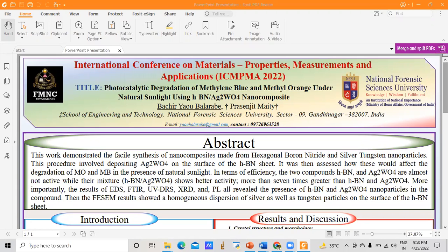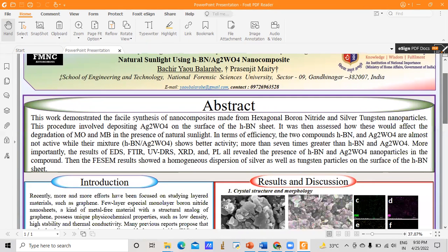So our topic is the photocatalytic degradation of methylene blue and methyl orange under natural sunlight using HBN-Ag2WO4 nanocomposite. This work demonstrates the facile synthesis of a nanocomposite made from hexagonal boron nitride and silver tungstate nanoparticles. This procedure involves depositing Ag2WO4 on the surface of HBN nanosheet. It was then assessed how this would affect the degradation of methylene blue or methyl orange in the presence of